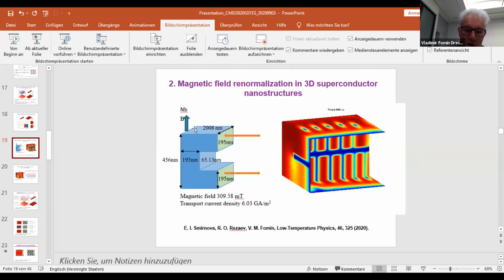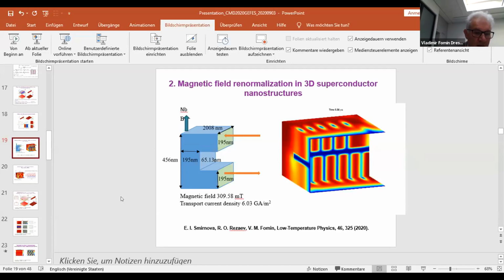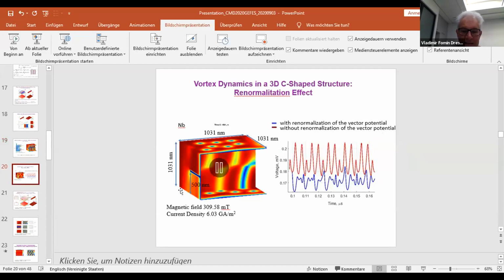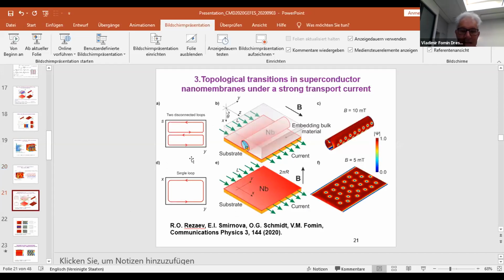And here, if this distance is large enough, these vortices practically do not feel each other. They are too far from each other, as is shown in this figure. But if these parts approach each other, the vortices try to feel each other, try to form one vortex line as expected, but nevertheless, due to the Magnus force, which flows through this structure, like in the tube, they nevertheless are separated, as is shown in this figure. And now I approach one of the key elements of my presentation. Recently, we considered a similar structure, but in the conditions when there is a strong transport current.